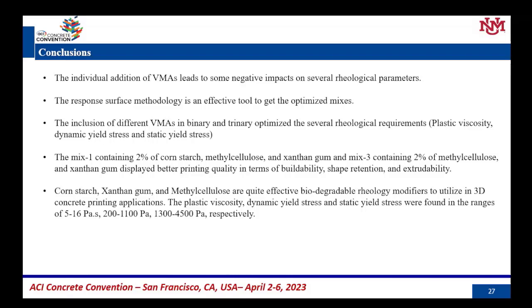So the best mixes in terms of printability were mix 1 and 3. Mix 1 contained 2% of cornstarch, 2% of methyl cellulose, and also 2% of xanthan gum. Similarly, the mix containing 2% of methyl cellulose and xanthan gum displayed better printability in all the criteria. Finally, it can be concluded that all these viscosity modifiers, cornstarch, xanthan gum, and methyl cellulose, are quite effective biodegradable mixes. And the ranges of the rheological parameters we found were 5 to 16 pascal second for plastic viscosity, 200 to 1100 pascal for dynamic yield stress, and 1300 to 4500 pascal for static yield stress.